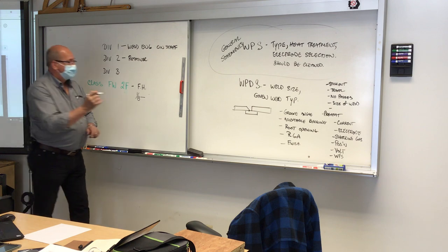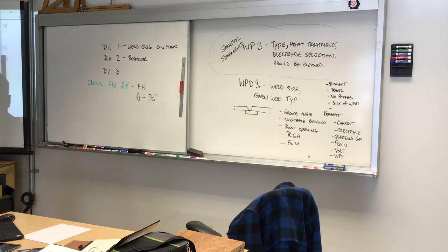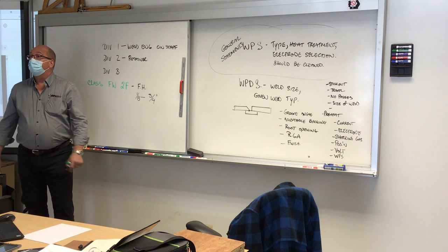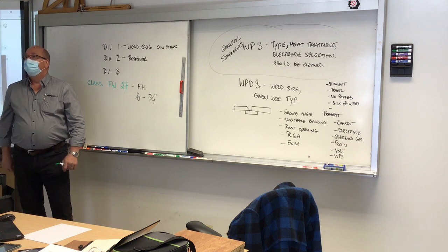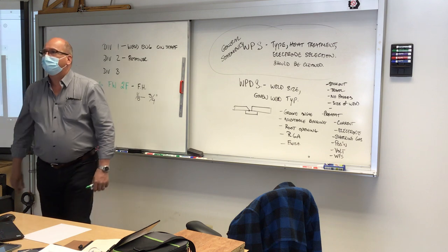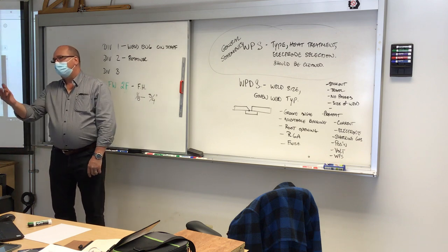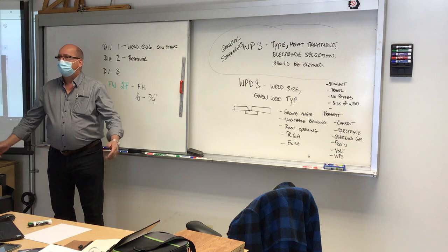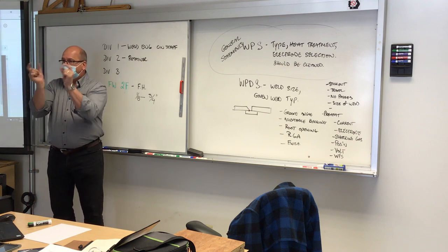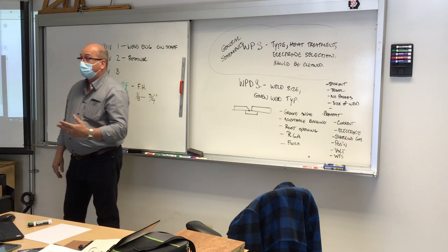This does. Inch and a half. Two times test. 3/8 test, 2 times test, 2T. So if I want to go to 1.5 inches, what do I do? Well, 3/4. Bingo! So am I going to make you do a 3/4 plate off the top? No, because it costs you more money. Now, can I bend test a 3/4 plate? Can I do a root bend on a 3/4 plate? No, because my punch and die don't work. They're made for 3/8 plates. Okay, so what do I have to do with 3/4 plate? I got to do side bends and or x-ray.